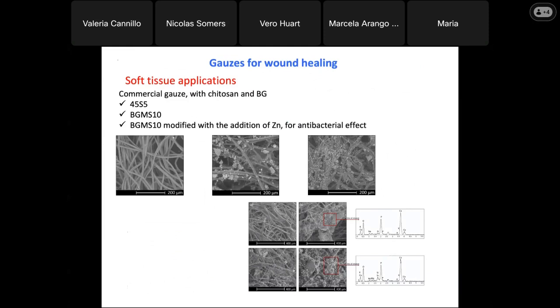Then coming to soft tissue applications, first of all, we produced gauzes for wound healing. So we started with a commercial gauze, which was impregnated with chitosan and bioactive glass. We used different compositions: as everywhere, 45S5 as a reference, and then BGMS10, and also BGMS10 modified with the addition of zinc, which is an ion known for its antibacterial effect, and the antibacterial effect is desirable for an application like skin regeneration or a gauze, to avoid infections.